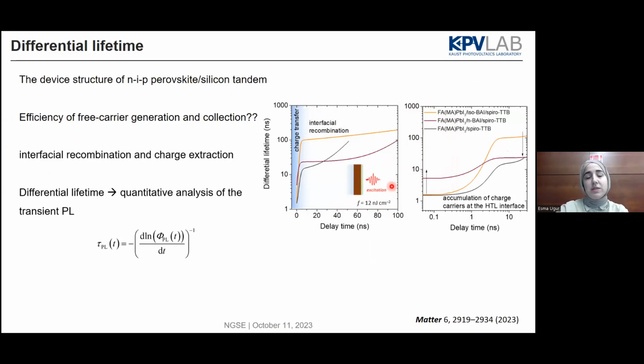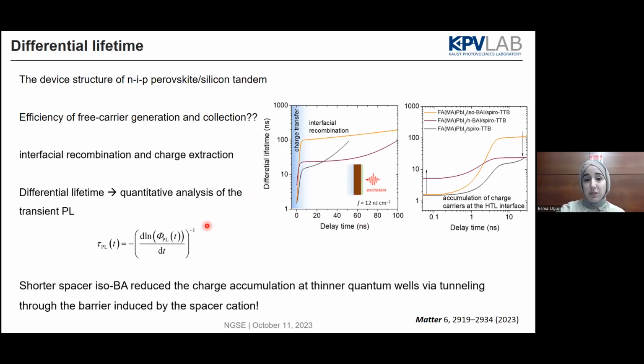that you can excite at really low fluences, so that you are not getting a contribution from the second or third order recombination. From the differential lifetime, you can separate, or at least have an idea about, the charge transfer or the interfacial recombination part. For instance, in the isobutylammonium one, it is reaching a plateau, which gives the information that you are passivating the interface compared to the control, and it is giving quite similar charge extraction to the control. On the other hand, the N-butylammonium shows a different behavior. It is really slowed down, so it slows down the charge extraction.